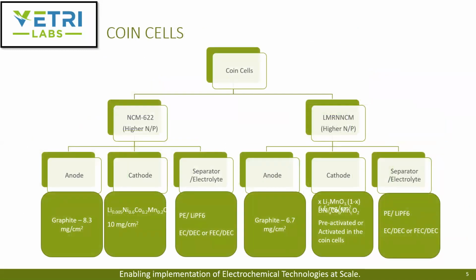On the coin cells, they focus on the negative to positive capacity ratio. They make sure that the materials of choice, both the NCM coin cells and the lithium manganese rich NCM materials, have a higher negative to positive capacity ratio. This is chosen to avoid additional failure mechanisms arising due to lithium plating. It's a smart way of controlling the test so they don't introduce additional side effects due to the cathode to anode capacity ratio.